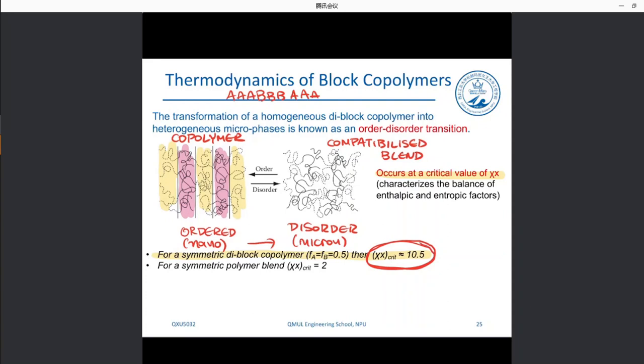For a symmetric polymer blend, you can see that this value is only 2, okay? Why is that? Why is it much smaller? Because we have a much higher loss of entropy in copolymers compared to blends, okay? And the entropy is proportional to the degree of polymerization, okay? So we have